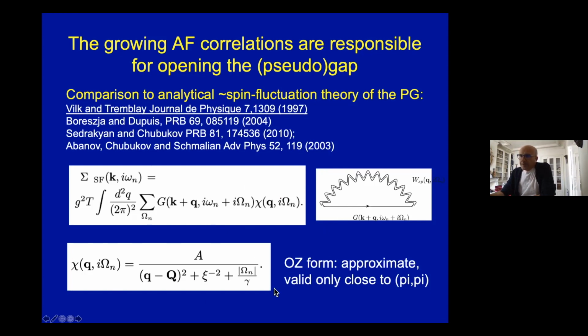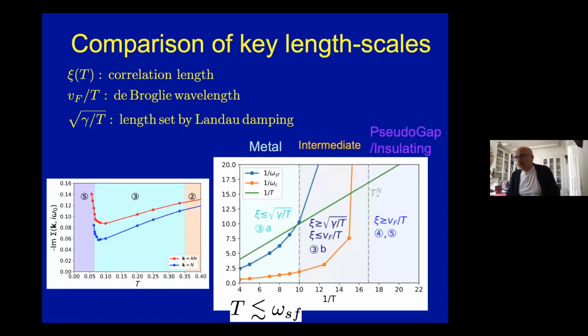And if I write some sort of Ornstein-Zernike plus Landau damping form for the spin susceptibility here, you see that there are two important scales in the problem. There is the correlation length, and there is another length scale which is set by the Landau damping, which is not very important in the low temperature regime, but which is important in the metallic regime. And this actually defines three regimes of temperature, just comparing these various scales together.